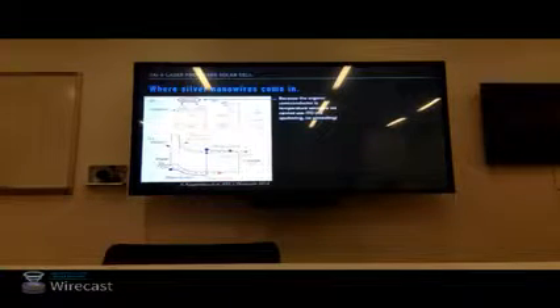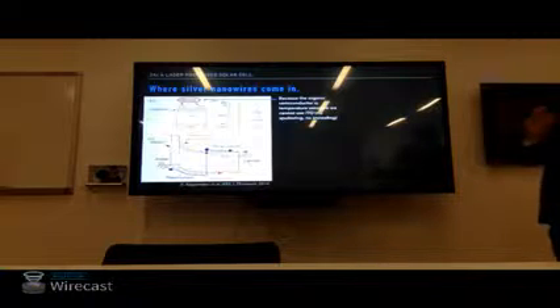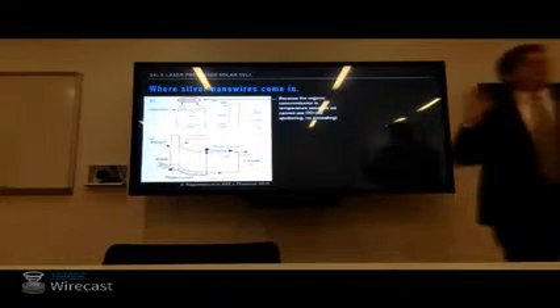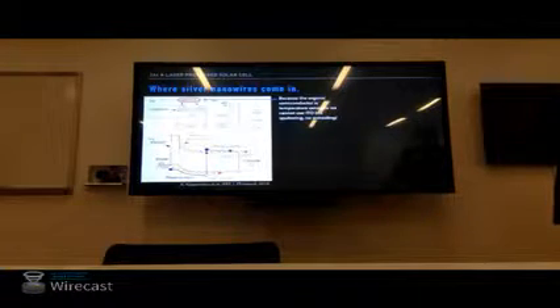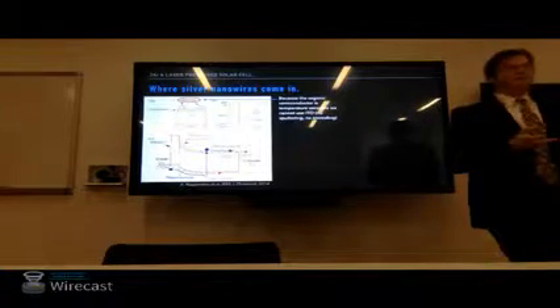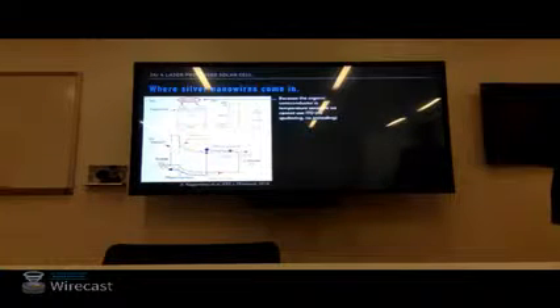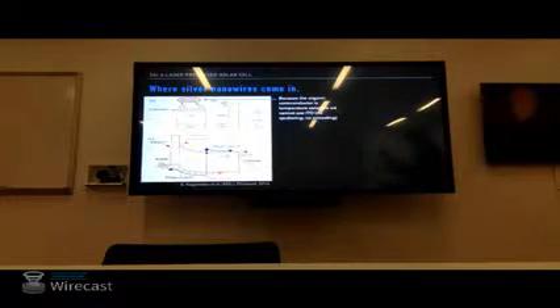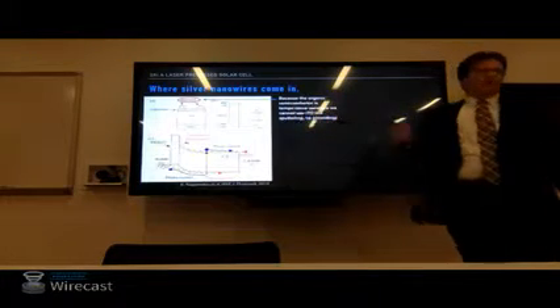Because the top layer next to the transparent electrode is an organic semiconductor, it's sensitive to high temperatures. That's why ITO can't be employed in this scheme. ITO typically requires a high temperature anneal, so we couldn't put this thing in a vacuum chamber and sputter ITO onto it. So right now they use a bus bar and finger grid.